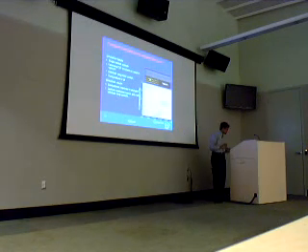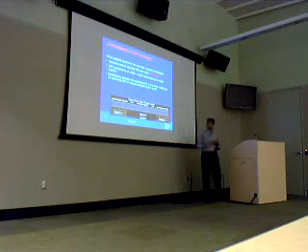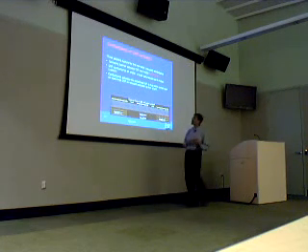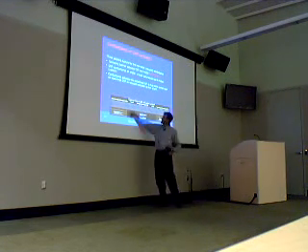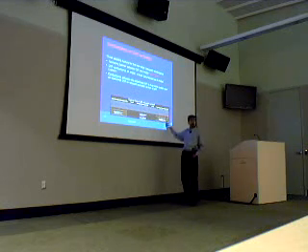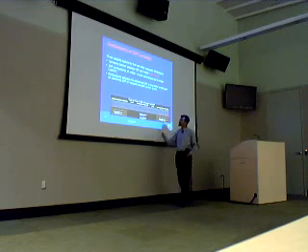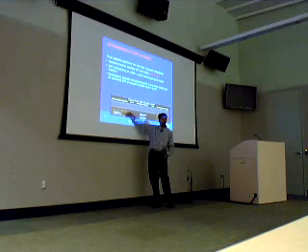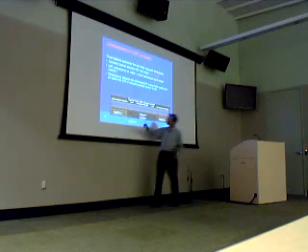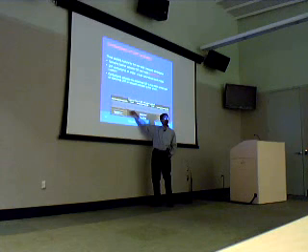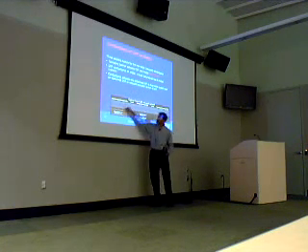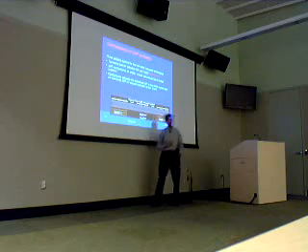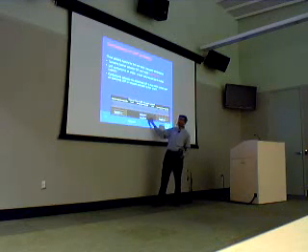And what was the reason for it? The reason can be looked at from three different components. This is a metal here, and this is the carbon nanotube going to the other side to a different contact. There is the metal to CNT interaction, the so-called contact resistance. Then the metal chemically interacts with the CNT where it contacts, so this part of the CNT deforms.